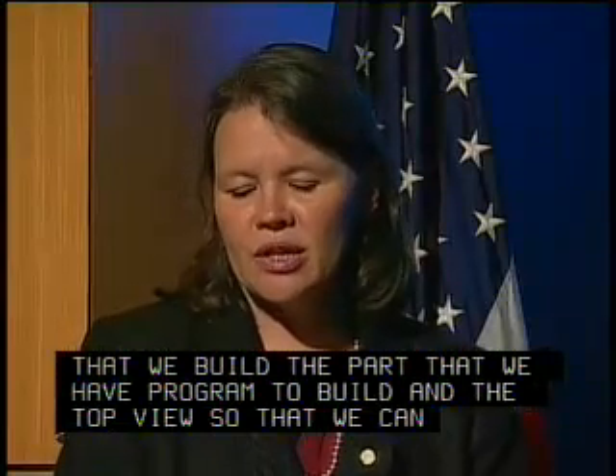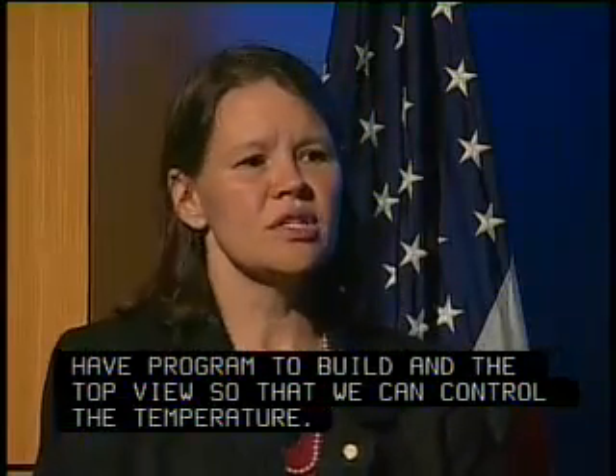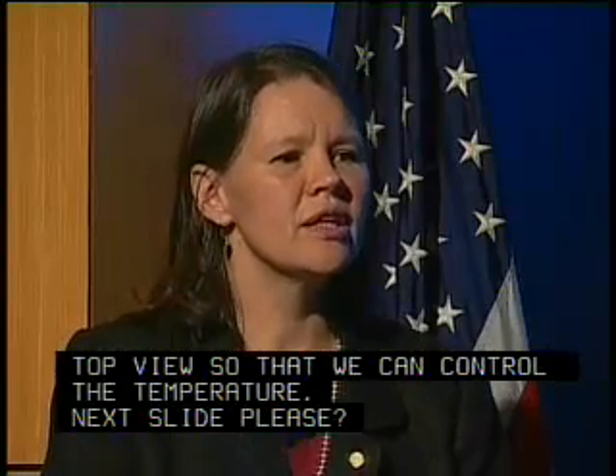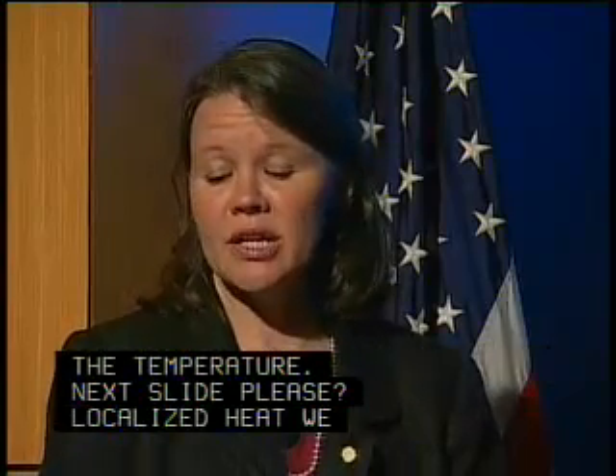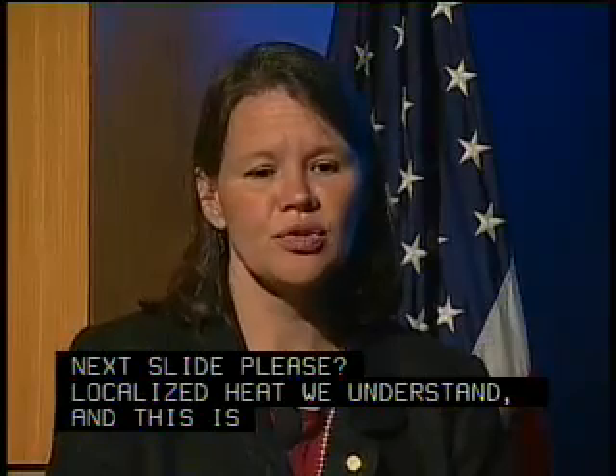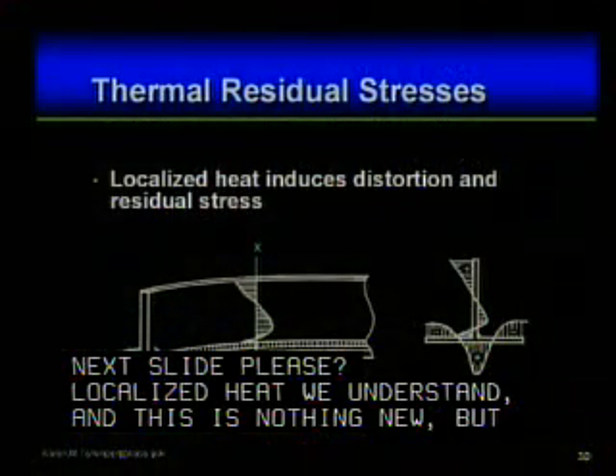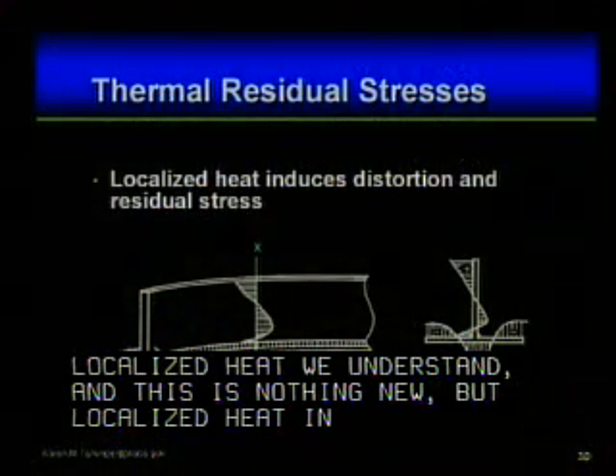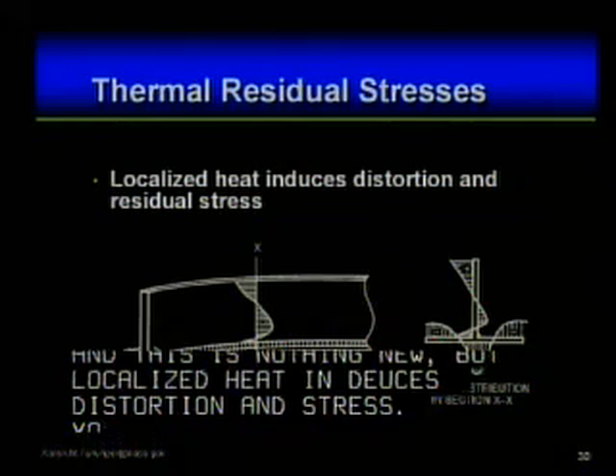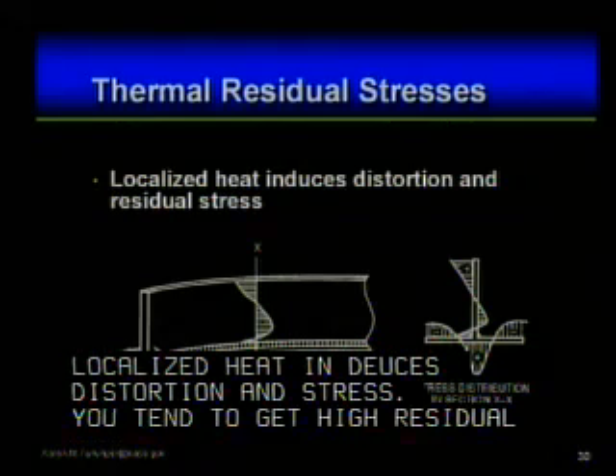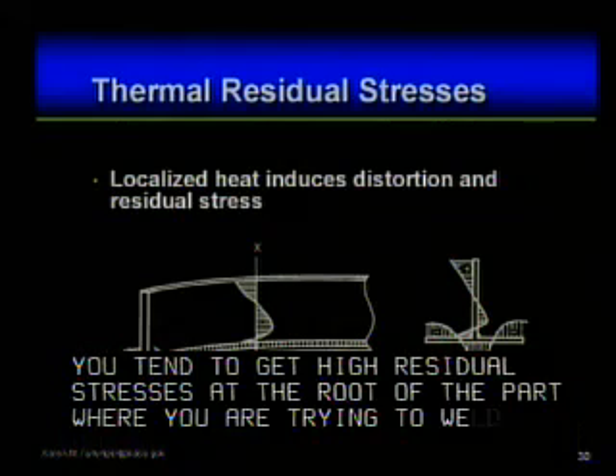Localized heat, we understand, and this is nothing new. This has been very commonly known for decades in the welding industry. But localized heat induces distortion and residual stress. You tend to get very high tensile residual stresses right at the root of the deposit, or of the part where you're trying to weld it on. And it just is trying to pull that deposit off of the base plate.